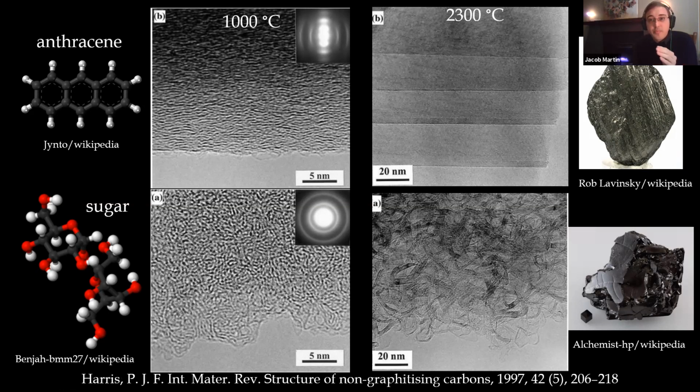Now, why is that weird? Most metastable forms of carbon, such as diamond, when you heat them to a couple of 100 degrees above room temperature, will rapidly decompose into the thermodynamically most stable material, which is graphite at atmospheric pressure. Glassy carbon, this material down here, is very odd in that even when you heat it to extreme temperatures, to 3000 Kelvin, it will actually vaporize before it converts to graphite. So the big question in the field has been what causes this structure to be so metastable, perhaps the most metastable material that we know of.